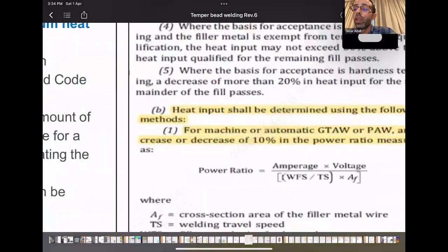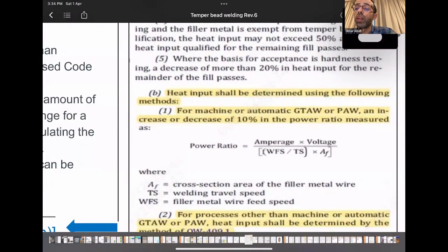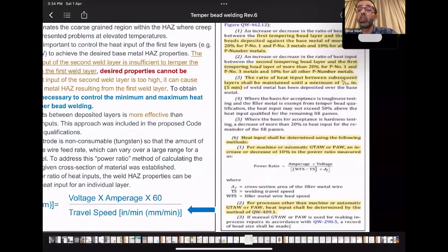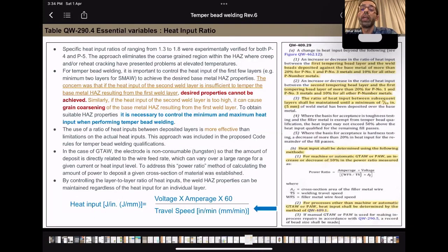And in the power ratio, we can see that you have the cross section of the filler wire and the filler wire feed speed. So it depends on the feed rate of the filler wire and the filler wire cross section. So this power ratio is to control the heat input ratio when using GTAW techniques. And of course, automated is a lot better in controlling the heat input or power ratio than manual technique, and that's the reason why it is preferred. And you have an additional requirement for using manual GTAW for temper bead as specified in section 9.